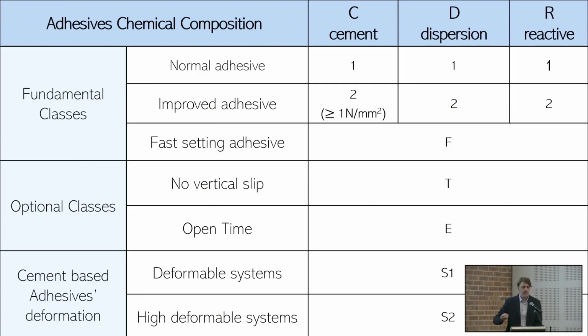So the most common instead is the cement C adhesive, and is divided in class 1 and class 2. Did you know that? Not all the cement are the same. Adhesive class 1, C1, adhesive class 2, C2. The C2 adhesive means that the pull-off resistance, so the force, the strength I need to detach the tile is 10 kilograms for every square centimeter. So if I fix a tile here with C2 adhesive, for every square centimeter, if I want to detach the tile, I need to reach 10 kilograms per square centimeter.